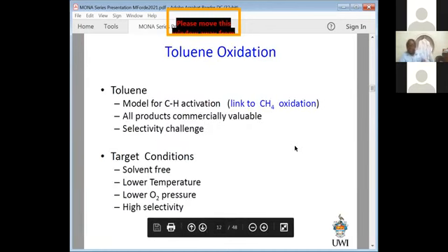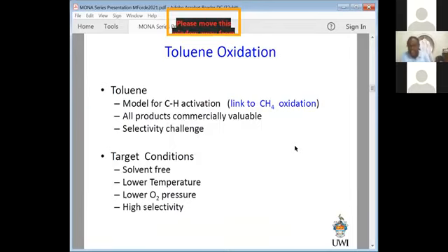So we start off talking a little bit about toluene oxidation, and this is one of the Odyssey stories, since my PhD was not in toluene oxidation actually, but I think one of my best papers was in toluene oxidation, which actually happened at the very end of the PhD into the postdoctoral research, right? And the idea behind it was that the toluene molecule has this methyl moiety in it, and those CH bonds can be activated only in special systems. And so it's a link to methane oxidation because, of course, methane oxidation has the same CH bond, albeit the strength of that bond is a little different in methane versus toluene. But the general idea is that if you can activate one CH bond, you can probably activate the other one.